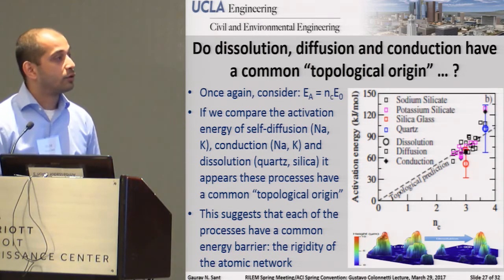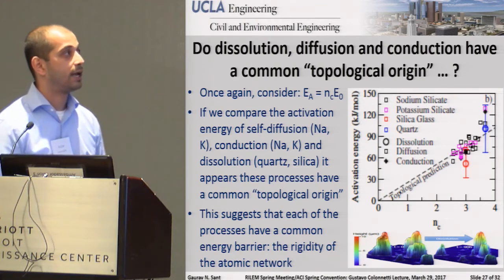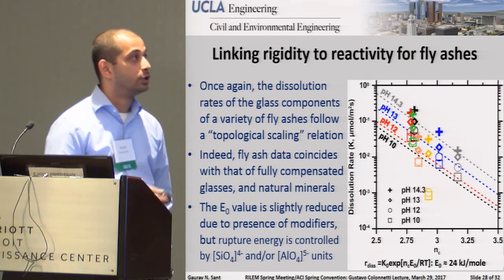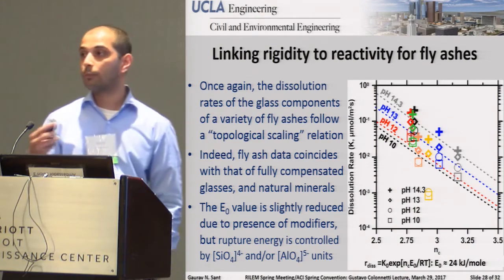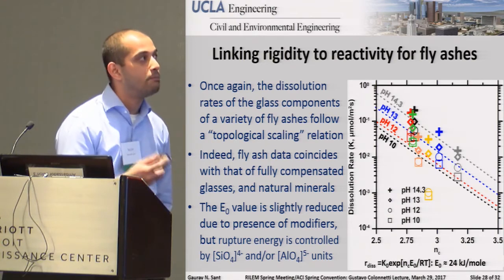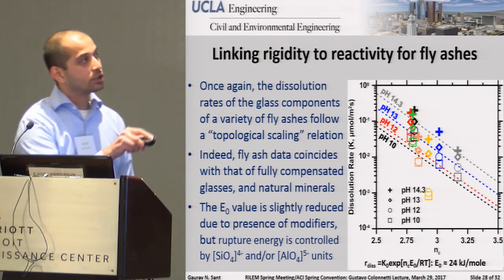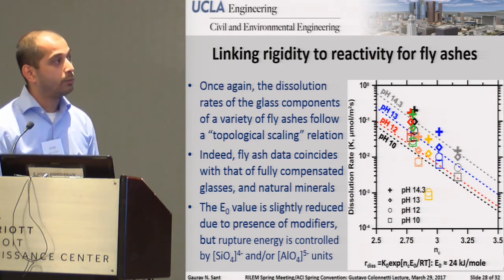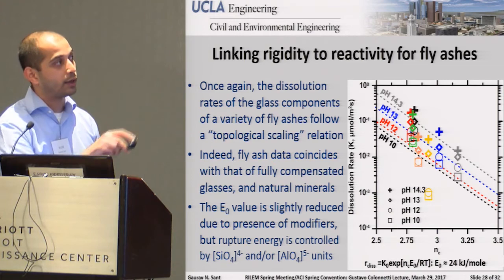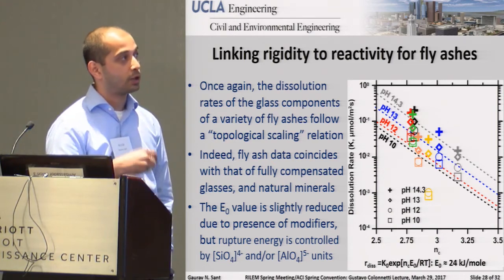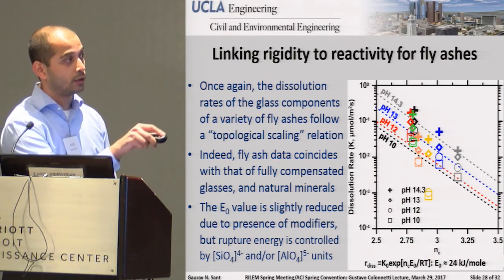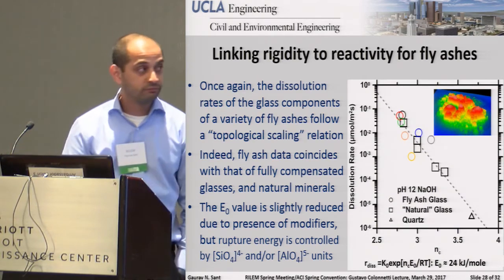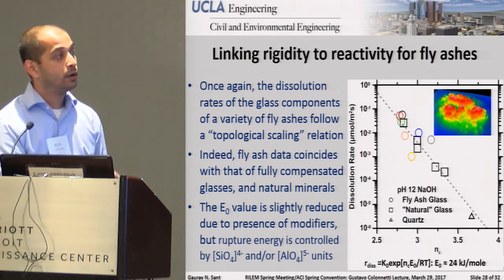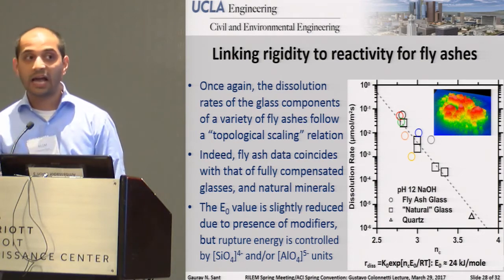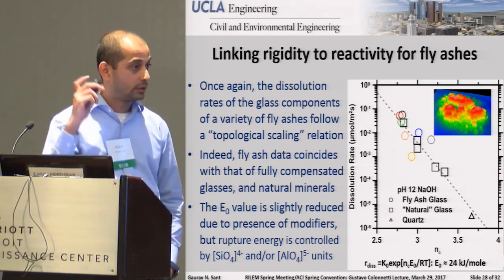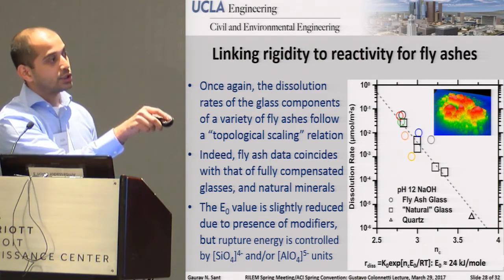Now, an important thing to point out, of course, is that if you go forward and start to look at the same thing applied to fly ash, you start to see something very interesting emerge. Once again, just like we saw with these, I'm going to call them pure solids, even if you take this rather messy glass system that you have in fly ash, the topological scaling relation does follow. Even if you take a step further and take all of the scaling that you've got right here, which is associated with the fly ashes, and plot the dissolution rate, for example, at pH 12 in sodium hydroxide, for fly ash glasses with that of natural glasses, such as sodium silicate glass, quartz, or other things like albite, jadeite and nepheline, which you can synthesize in a glassy form, this topological scaling relation actually still holds quite well.